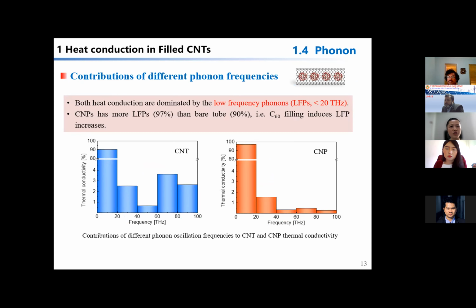From these slides, it is shown that the thermal conductivity of the bare tube, the left picture, and the nano-peapod, the right picture, are both dominated by low frequency phonons, less than 20 THz. And with filling, the assembled structure has more low frequency phonons than the bare tube. It can be up to 97%. That is, carbon-60 filling induces a low frequency phonon increase.